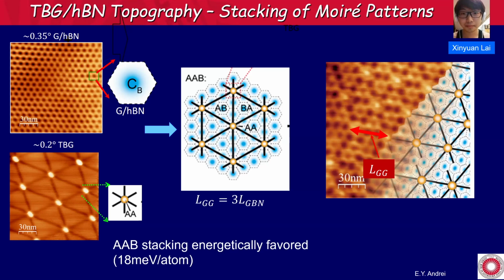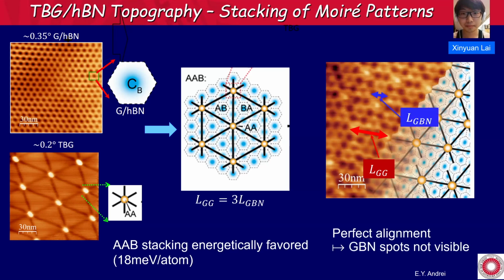The lattice spacing for twisted bilayer graphene, and the distance between the dark spots gives you the lattice spacing of graphene on boron nitride. And then we can go to reciprocal space, calculate KGG, KGBN, calculate the actual twist angle, get the strain. There's a lot of stuff that we can get out of this. Okay.